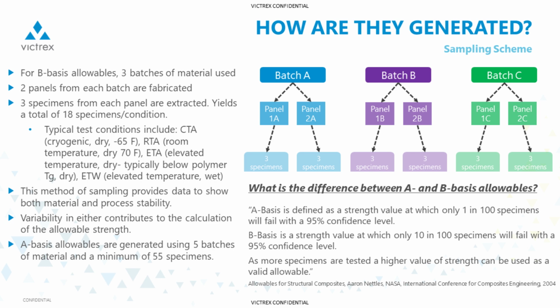So how are allowables generated? They're generated using generally a minimum of 3 batches of material. 2 panels from each batch are fabricated, and 3 specimens typically are extracted from each panel to create a set of minimum 18 specimens for each test and condition.